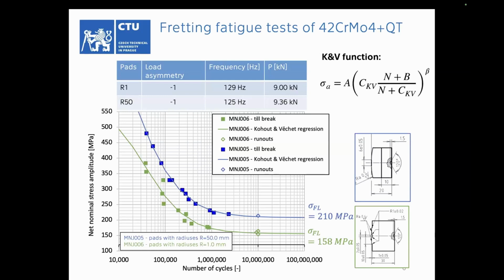These are the resulting SN curves for the two pads and the fatigue limits evaluated from them. The test conditions are listed in this table. Load asymmetry is -1, frequency around 130 Hertz, and pressure force around 9 kilonewtons. These data are fitted by the Kohout and Věchet function, which is shown here.